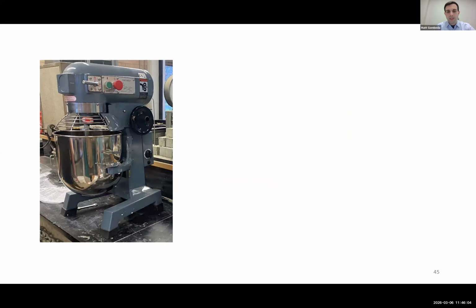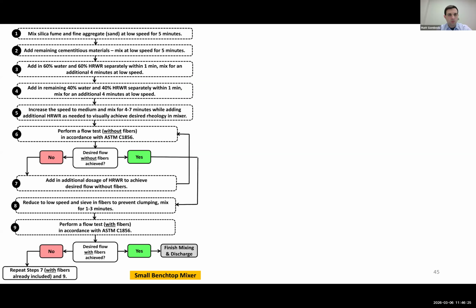So what we did is we basically re-engineered some of these mix designs for non-proprietary mixes to be able to be used with local materials in Illinois. And it started on a benchtop scale again with the small cube specimens using this mixer here. And we developed this method of when to add the materials, how long to spin the mixer, and then how to evaluate the performance at different steps before we get to the bottom where we would discharge and make specimens.